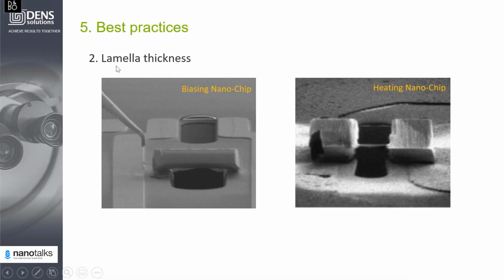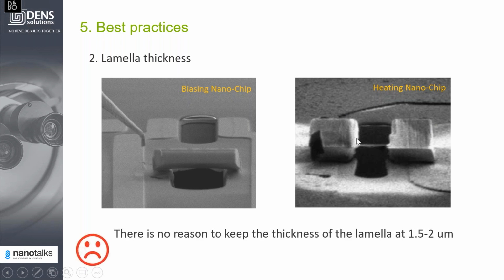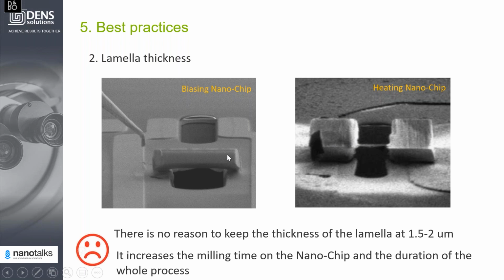So the next point is about lamella thickness. Here you see examples of relatively thick lamellas on a biasing nanochip, and this is on a heating nanochip. Frankly speaking, you don't really need to prepare lamellas thicker than one micron. So you don't need to prepare 1.5 to 2 micron thickness. The issue is that you will increase the milling time on the chip, which will complicate the whole process.